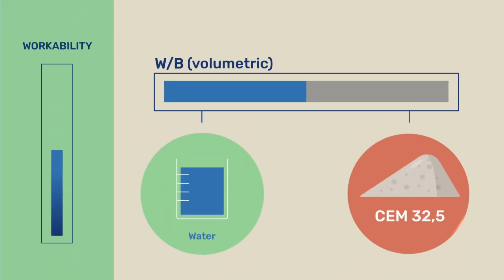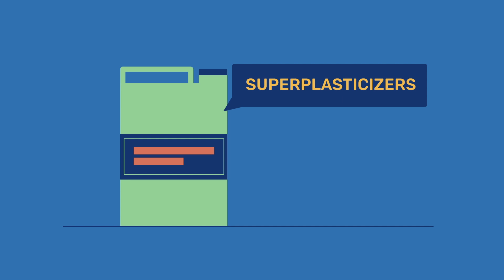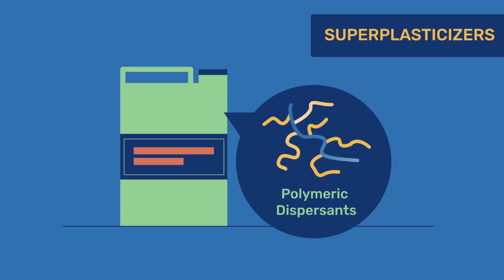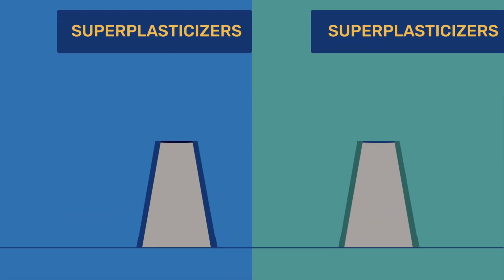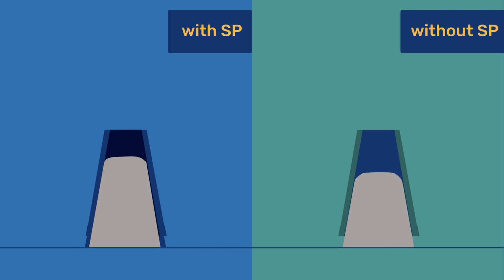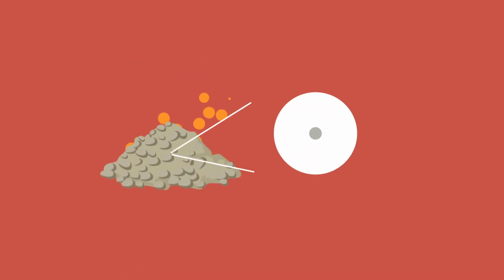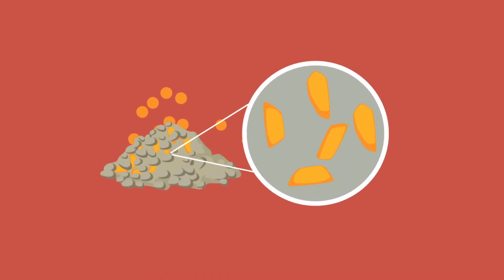However, water reduction comes with the cost of worsened workability. In many cases, this may be remedied by superplasticizers, a type of chemical admixture based on polymeric dispersants, which added in very small amounts, in the range of some fraction of a % of the cement mass, lead to a major change in fluidity. Additionally, changing the grading of sand and aggregates can be beneficial.